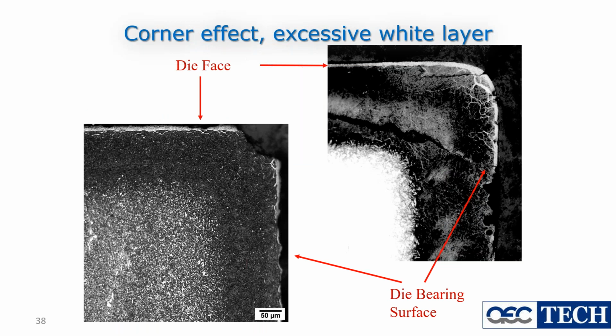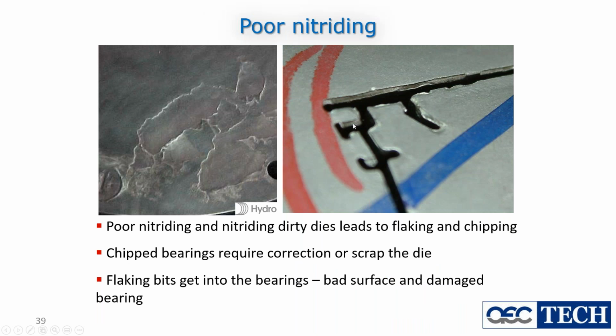If we look at the corners here, when you get right to the corner, you've got nitrogen coming in this way, up and down, but you've also got nitrogen coming in from the side. And if you're over aggressive with your nitriding, you can produce this extra layer of the wrong phase, because the corner is subjected to twice as much nitrogen coming in as the straight faces. This causes microcracking, it's weak, and as soon as it hits an extrusion, it chips out and looks like this. And this is what it will look like on a die.